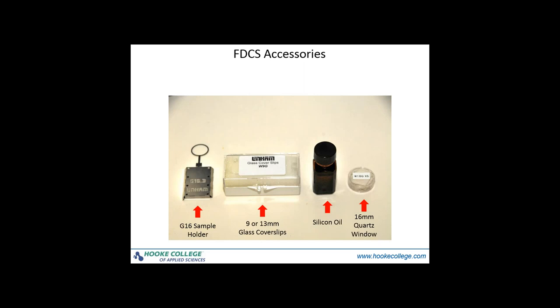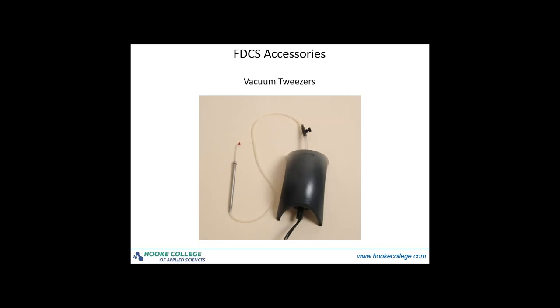We'll place only 3 to 5 microliters of sample, that is all that you need, on top of the 16-millimeter quartz window, and then we would place this 9-millimeter or 13-millimeter glass cover slip on top of our sample. And then we would actually freeze dry from the outer edge of the cover slip into the center. This is an accessory that comes with the system. It's the vacuum tweezers. This makes sample loading, especially with those 9 and 13 millimeter glass cover slips, very easy to do.